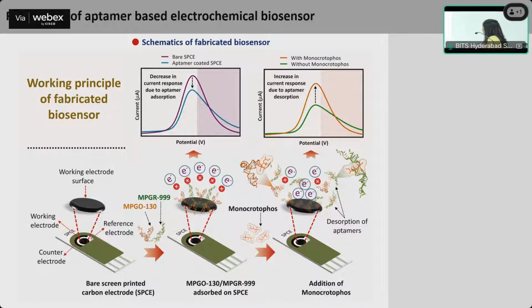Basically, you can see in case of bare SPCE, there is a decrease in the current observed when the aptamer was coated onto the electrode surface, and when there is monocrotophos, an increase in the current was observed. So we were expecting to get such kind of results in the electrochemical performance. All the parameters were optimized for efficient functioning of the electrodes, like scan rate and pH, and then both the aptamers MPGO-130 and MPGR-999 were also tested for different aptamer concentrations, and testing with monocrotophos was also carried out at different concentrations. With this, the LOD observed in case of MPGO-130 is 0.38 nanograms per ml, and in case of MPGR-999, it was 0.78 nanograms per ml.